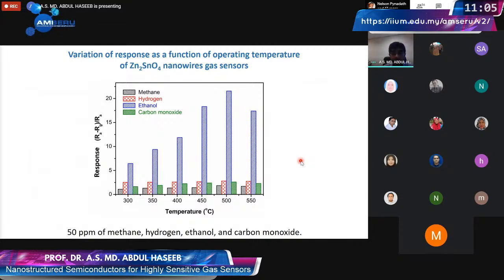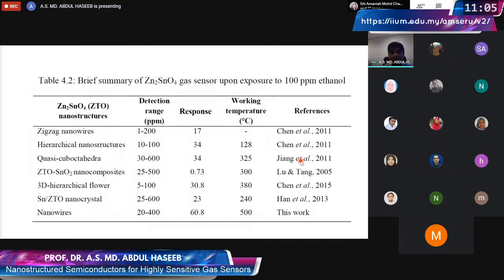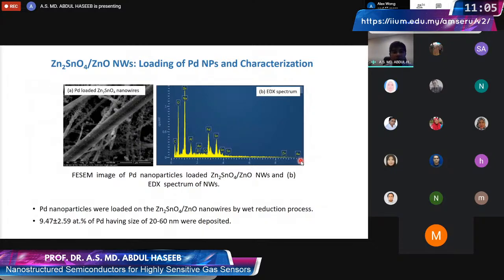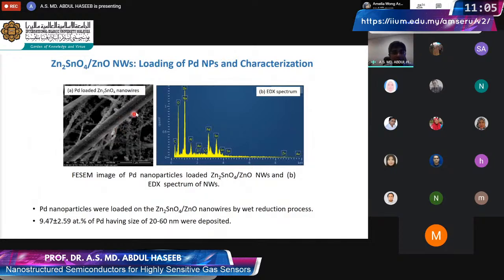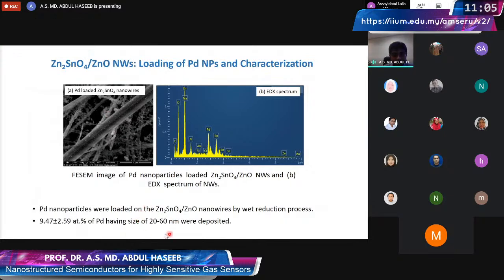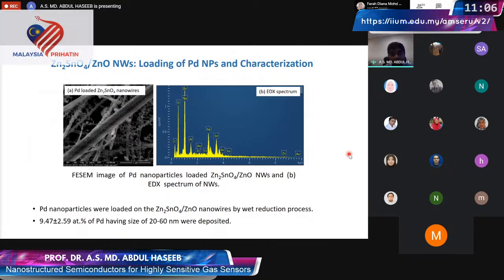Now, this sensitivity, is there any way to change that? For instance, we also know that a hydrogen sensor is getting very important. So what we did is we loaded those nanowires with palladium. It's a noble metal nanoparticle, by a chemical reduction route. I will not mention them. And we deposited about 20 to 60 nanometer particles all over the nanowire. And we did the gas sensing measurement once again.